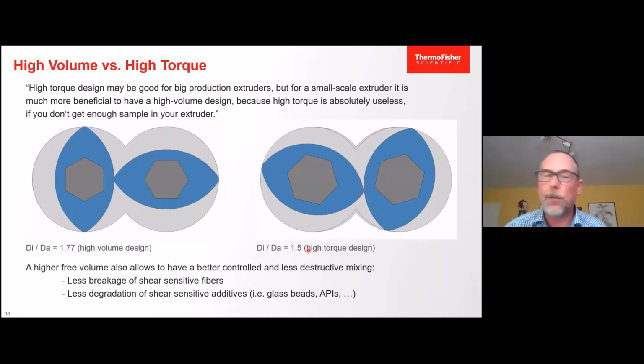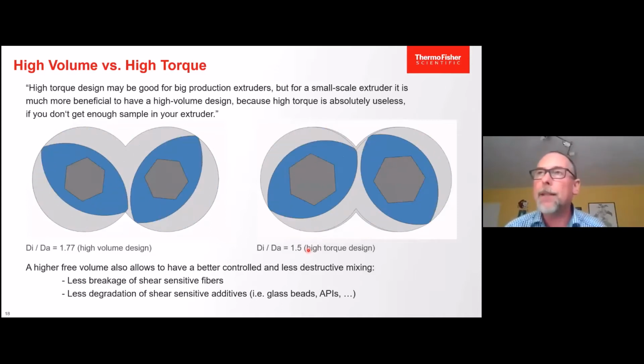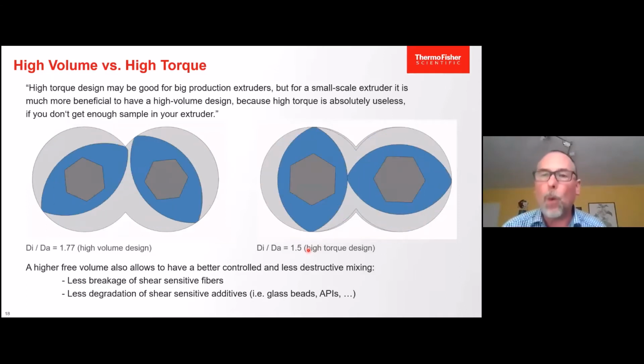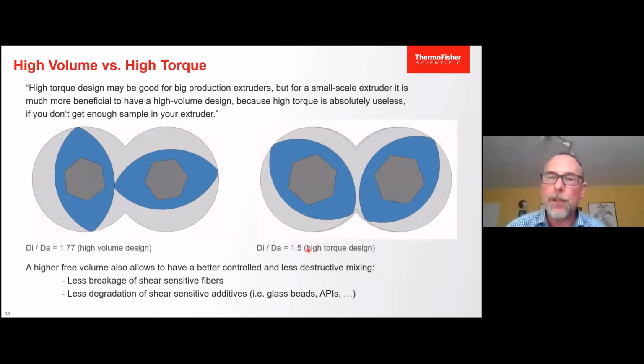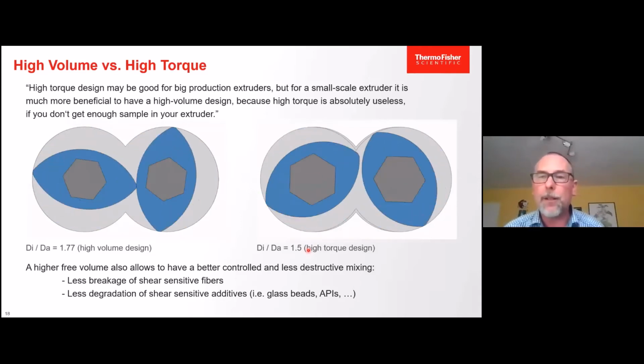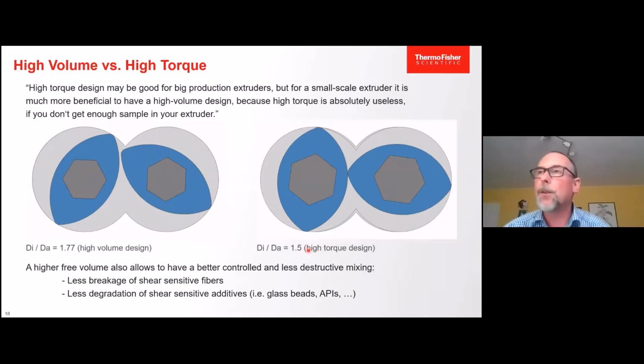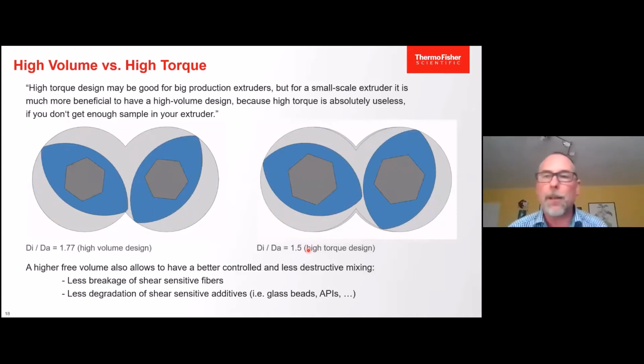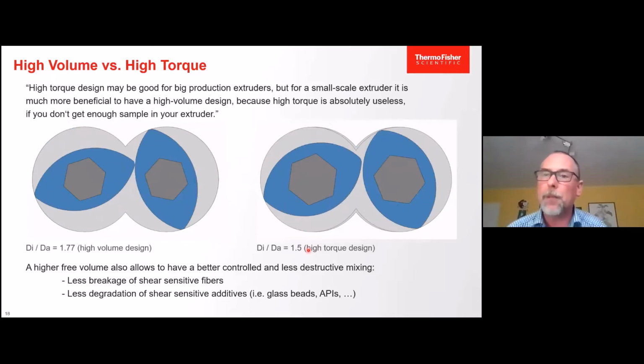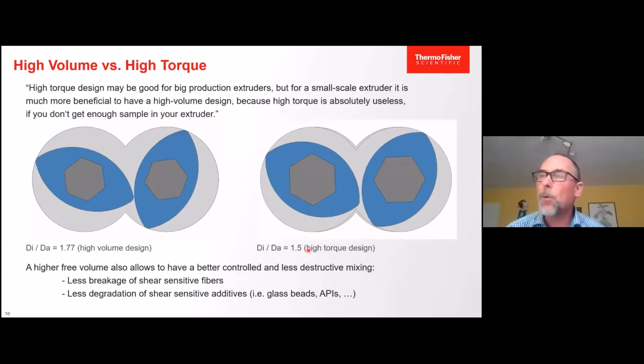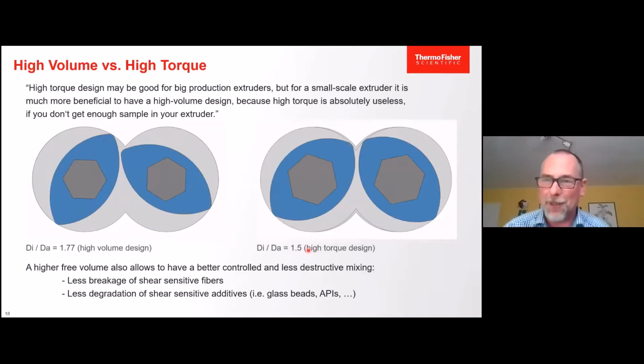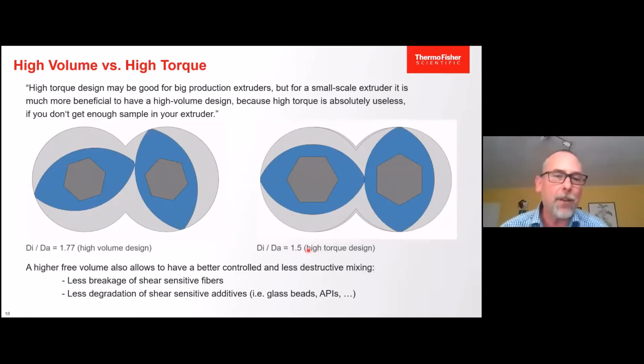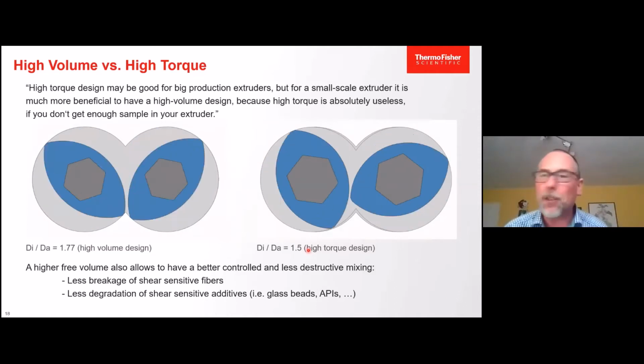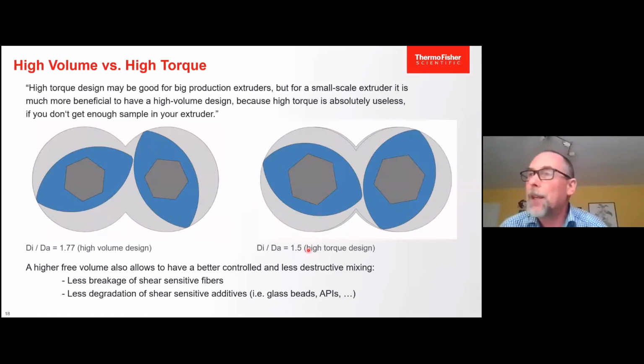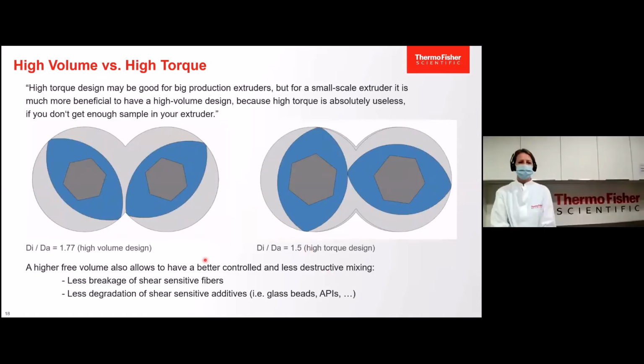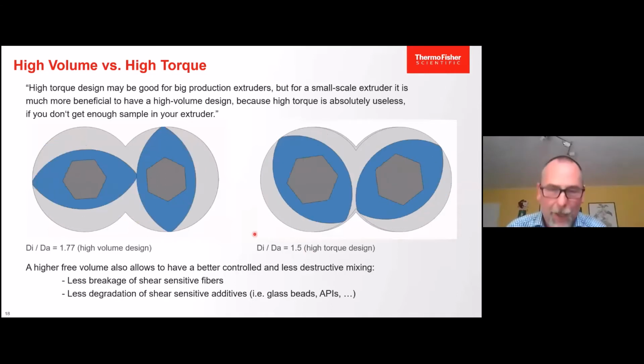For small-scale extruders, it is always a balance between what is the highest volume we can feed our material versus a high torque. High volume is good for small-scale processes, is good for bulky powders, is good for something like recycling materials, materials which come in irregular shape. So we need volume to feed those elements, the materials. And you know what goes into the extruder can come out. What doesn't will not come out, and the whole process will not really work. So it's a balance, what we consider as the highest volume and saving on some metal.